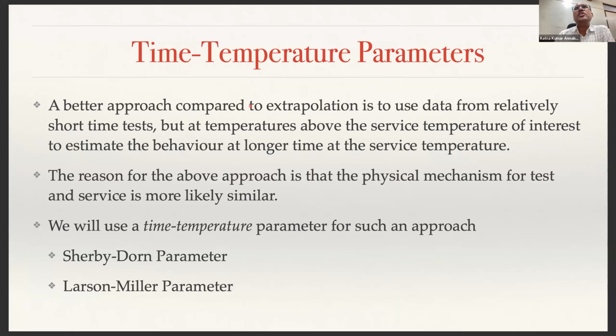So in order to avoid this extrapolation, there are some better approaches that people have suggested. You have to use data from relatively short time tests, but at temperatures much above the service temperature. So instead of operating at your service temperature, you will operate for a shorter period of time but at a higher temperature. So why do we do that? Because the physical mechanisms for test and service are more likely to be similar when you are operating at high temperature. So here we will use two parameters for life computation, the Sherby-Dorn parameter and the Larson-Miller parameter,